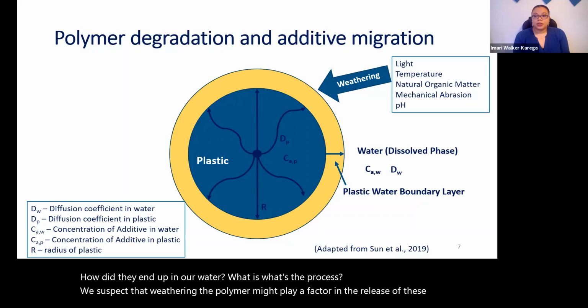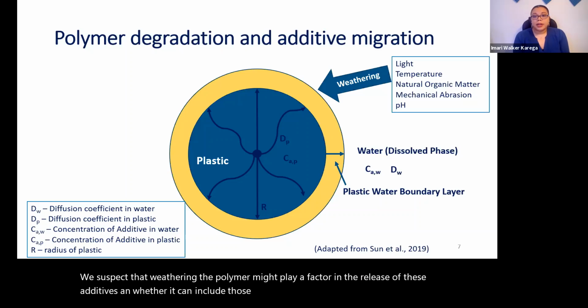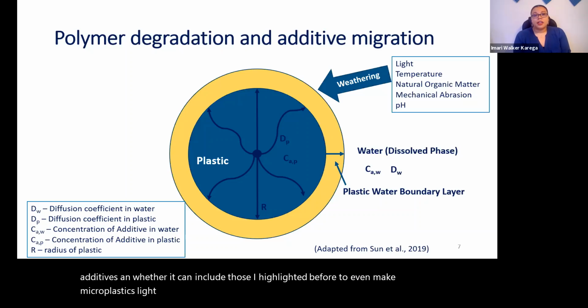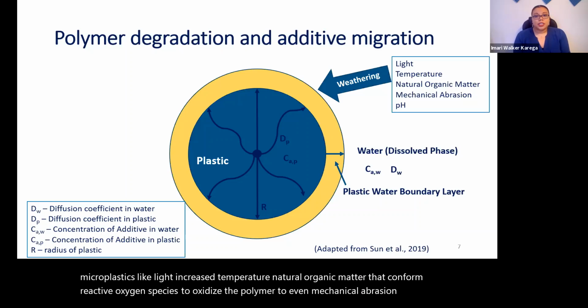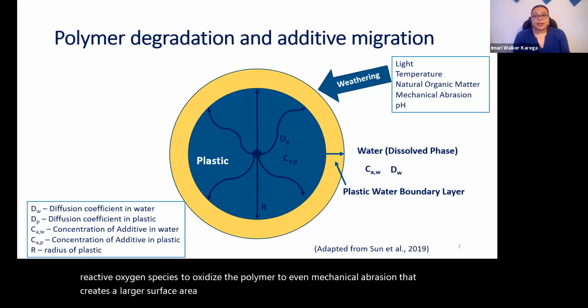Weathering can include those I highlighted before to even make microplastics, like light, increased temperature, natural organic matter that can form reactive oxygen species to oxidize the polymer, even mechanical abrasion that creates a larger surface area to release these polymer additives, along with pH, which can drive acid or base catalyzed hydrolysis on the surface of the polymer.